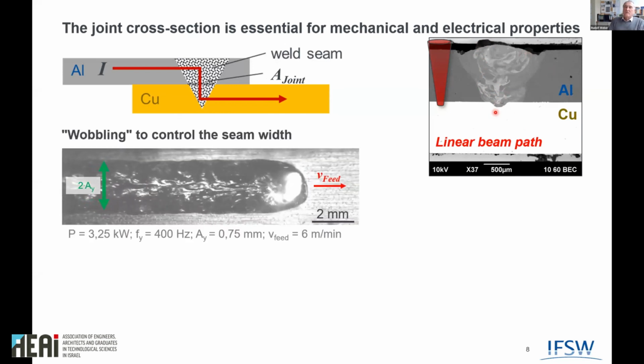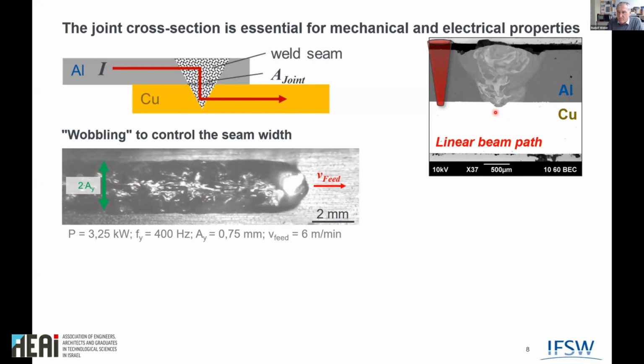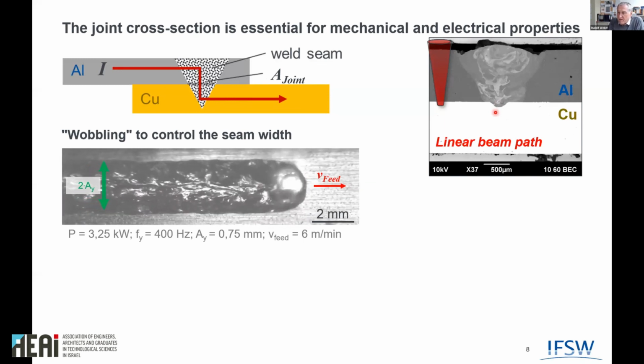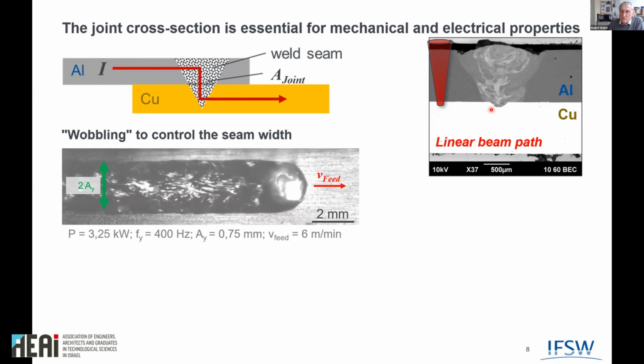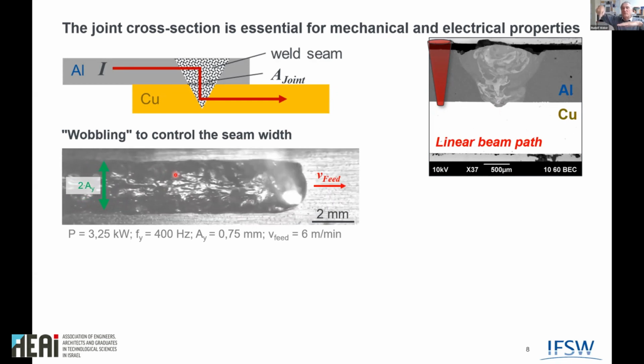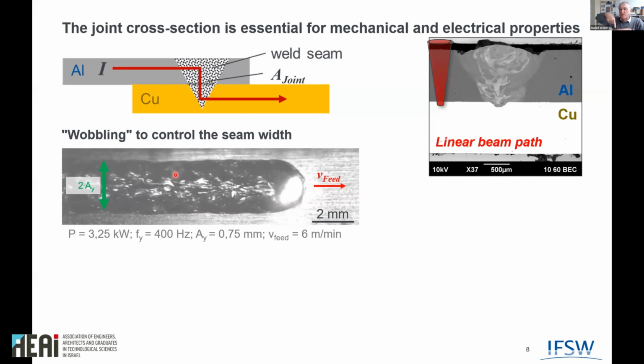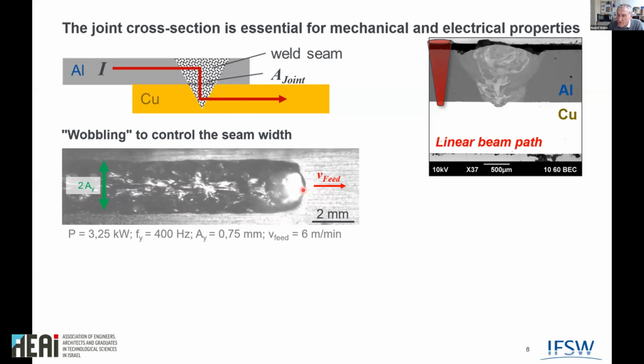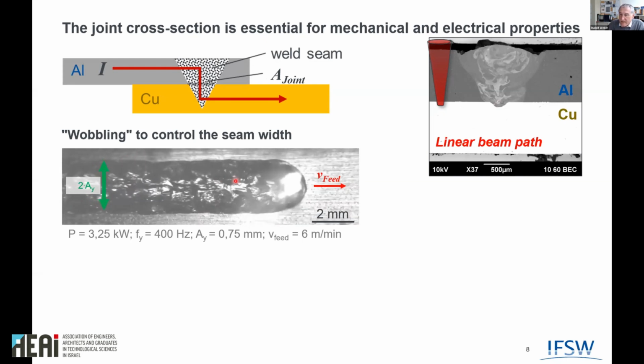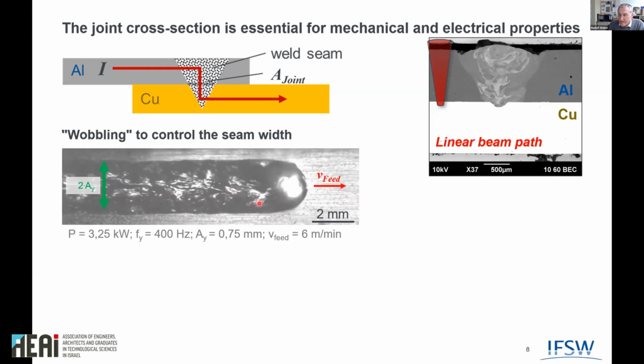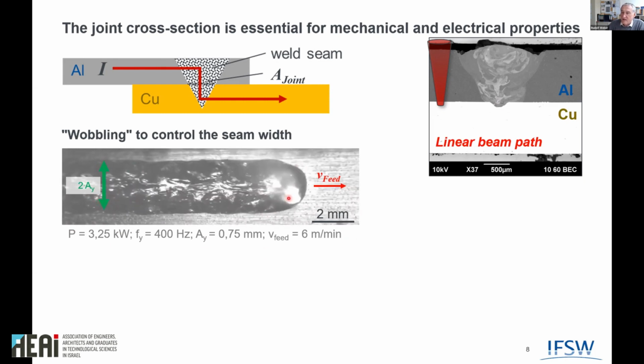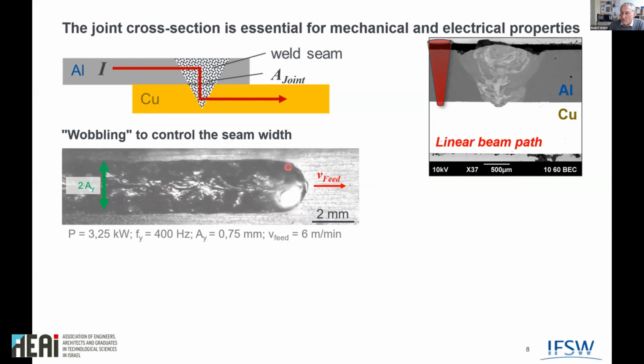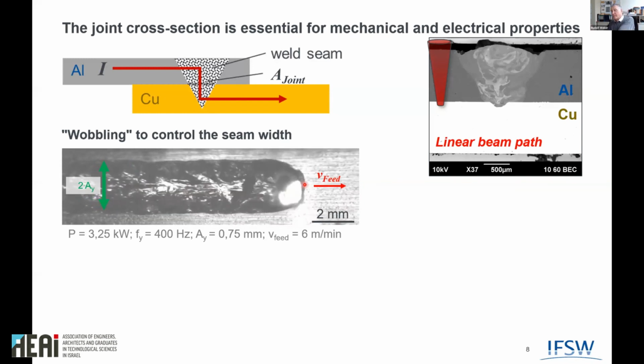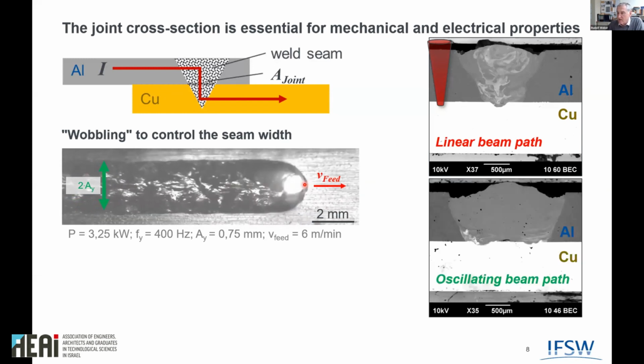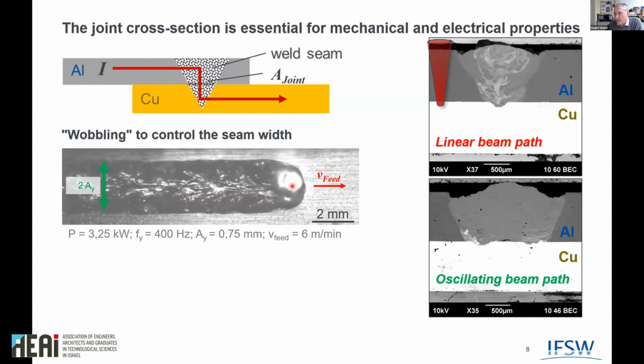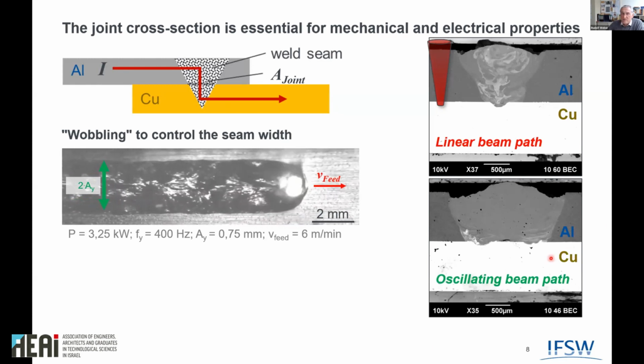And now what you can do, one of the most simple beam shaping things, is you do wobbling, which means that during the moving of the beam, you have an additional movement of the beam perpendicular to the direction of movement. So this then ends up with a quite wider weld seam. Here are the parameters for those who are interested. And you can see that the beam is moving here from left to the right, while the whole beam then is moving from bottom to top, while the whole thing is moving to the right. And this is how then the weld looks like.